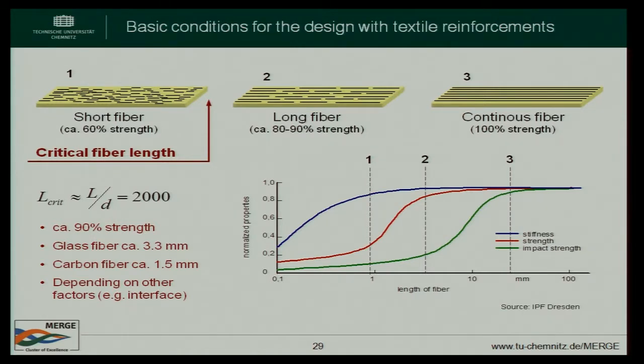So as you can see here, related properties, you reach already a nice level if you have a fiber length, let's say of 1 millimeter for, let's say, thermoplastic parts injection molding. So longer fibers are sometimes not necessary if you look at stiffness. Of course, for your strength, it makes sense to have a little bit longer fibers, in the range of 1 to 10 millimeters. By increasing the fiber length, you get better properties in the impact, so crash, energy absorption. So it's totally necessary to have long fibers.